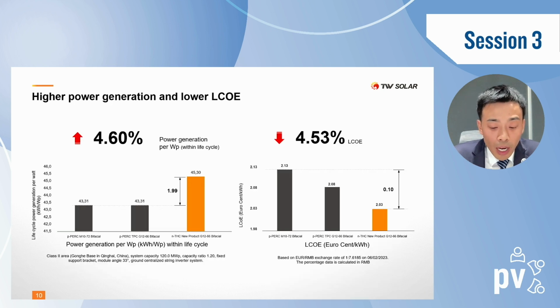Also, due to higher bifaciality, higher low irradiance performance, lower annual degradation and temperature coefficient, power generation per watt during the whole life of the THC module in the field will be 4.6% higher than that of the PERC module. Combined with the lower BOS because of the high module power, the LCOE of the THC module will be decreased by 4.53% compared to the M10 PERC module.